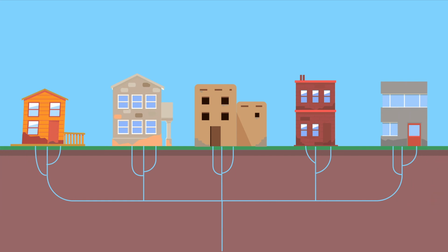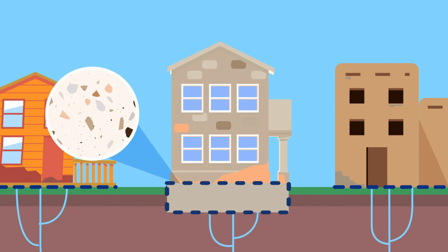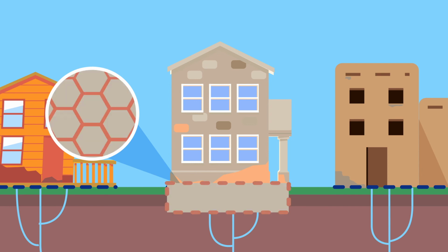Other important means of mitigating problems with the ingress of capillary water include cutting off its source from the sorptive materials. This can be achieved by using dense, poorly sorptive materials such as granite in basements of stone buildings. Similarly, polymer membranes can be used to limit contact with the groundwater.